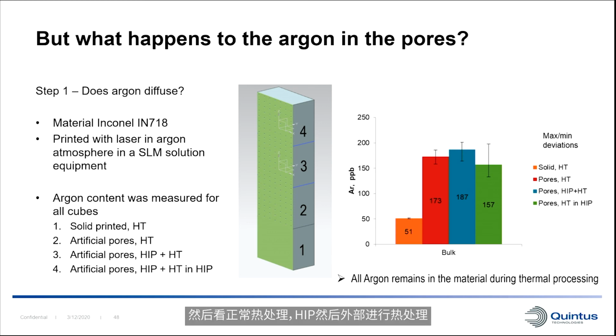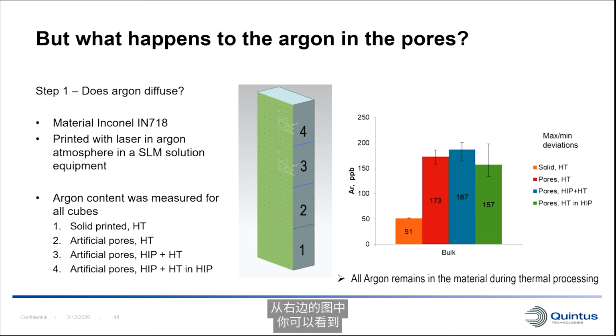And then looked at this with normal heat treatment, with HIP and then heat treatment externally, and then HIP with high pressure heat treatment inside the HIP. And from the graph on the right here, you can see that the fully dense printed material has a little bit less argon in it, but we can also see that the argon does not diffuse out of the product with any of the other processes. So we know the amount of argon there based on the pores that we printed on purpose.